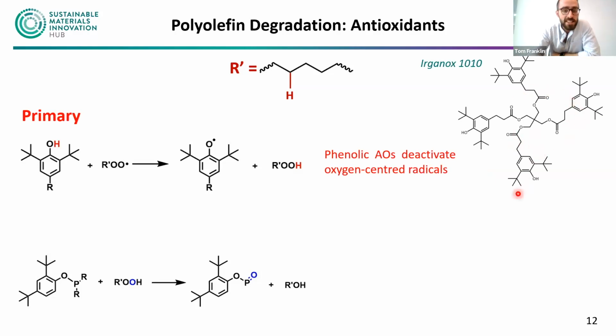The key is actually this hydrogen here, it's under a phenolic group. This hydrogen is effectively sacrificed for the greater good of the polymer. So the polymer chain is left untouched, but the additive sacrifices the hydrogen and stops that radical from being generated. But that still leaves you with radical species, less reactive, but can still react and cause damage.